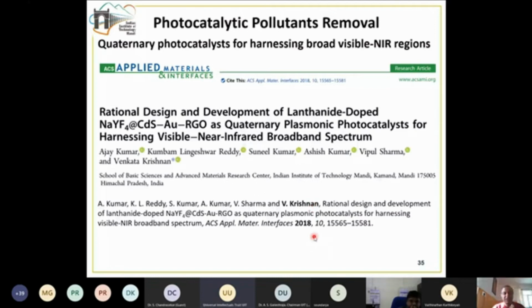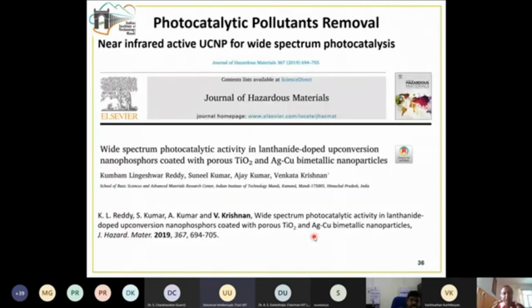So in the next work, we prepared a wide spectrum photocatalyst, wherein we can use the UV region, visible light region, and also the NIR region, and also with slightly low cost materials. Instead of gold, we went for silver copper bimetallic nanoparticles, which are also plasmonic in nature under visible light radiation. We went for the TiO2 material, which is a UV active photocatalyst, and then again this upconversion nanophosphor. And in the upconversion nanophosphor, we used a different combination, which is the ytterbium with thulium, which is a UV active material. So we have prepared this wide spectrum photocatalyst.